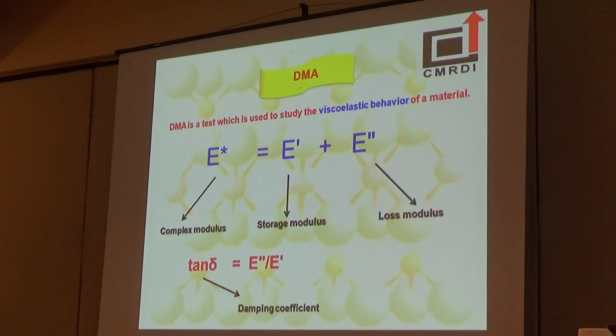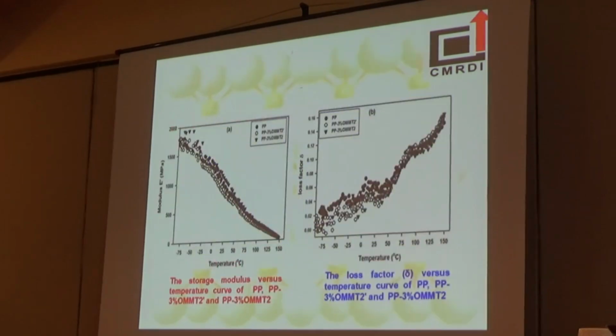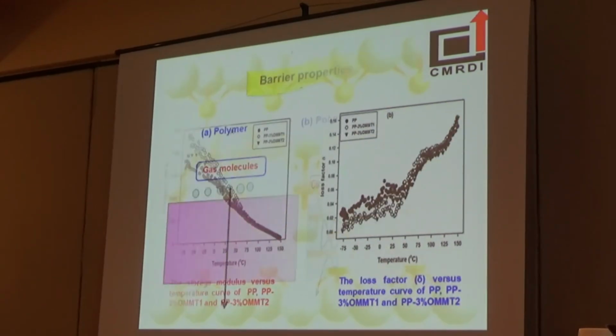Dynamic mechanical analysis is used to study the viscoelastic behavior of the material, where the complex modulus equals the sum of the storage modulus and the loss modulus. The ratio of the loss modulus to the storage modulus equals the damping coefficient, and if it is greater than 1, this means that the viscous part of the material is the one which determines its characteristics. By plotting the modulus versus temperature and the damping coefficient versus temperature, we can see that the sample which has a compatibilizer has the highest value of storage modulus and the lowest value of damping coefficient. The same is observed for all the prepared samples.